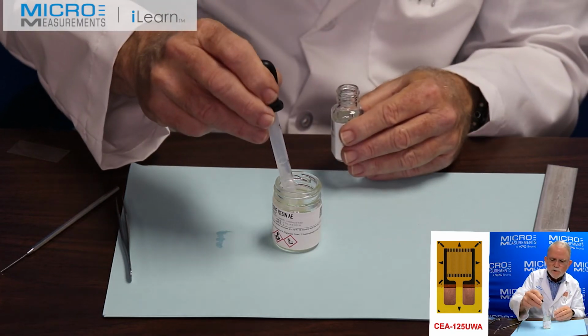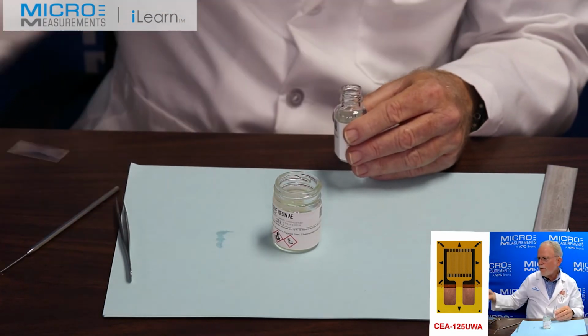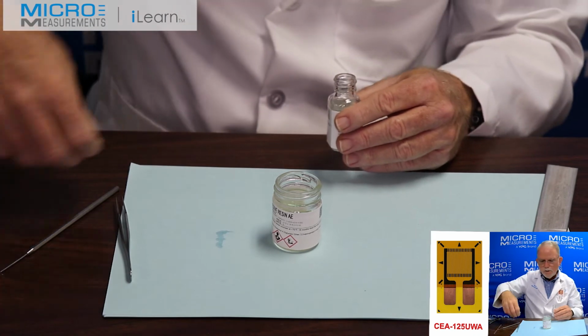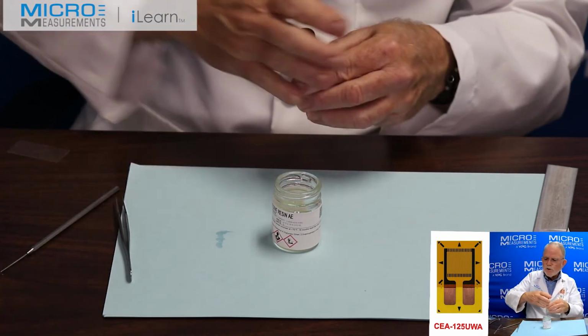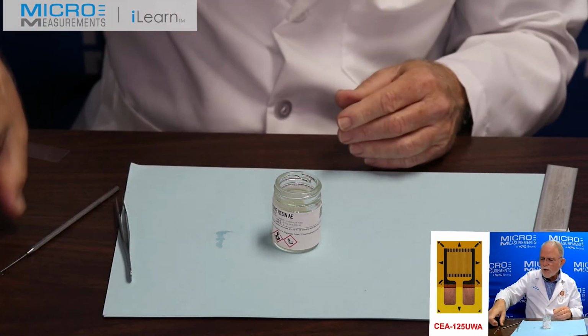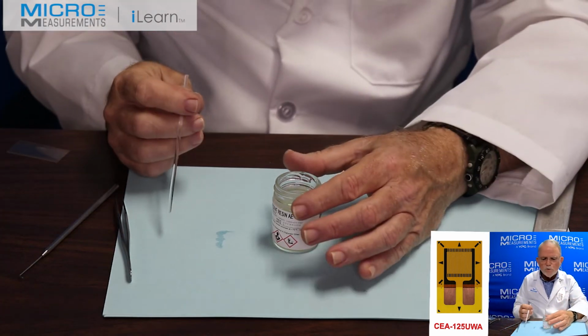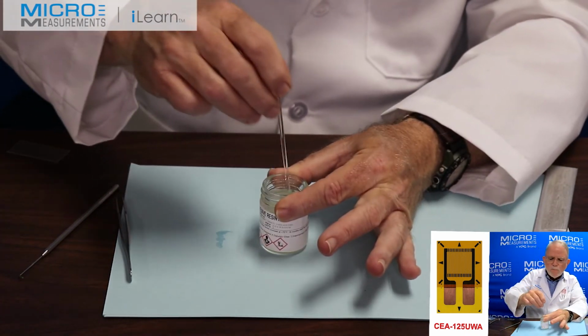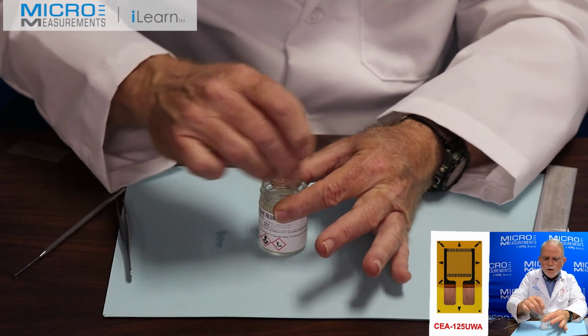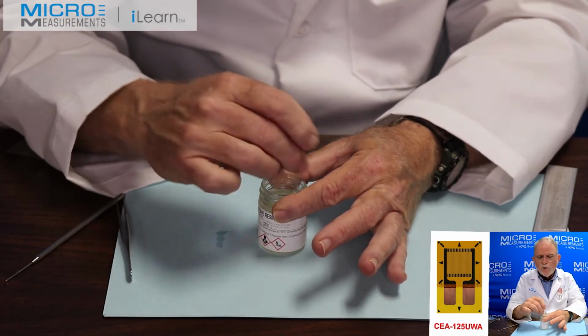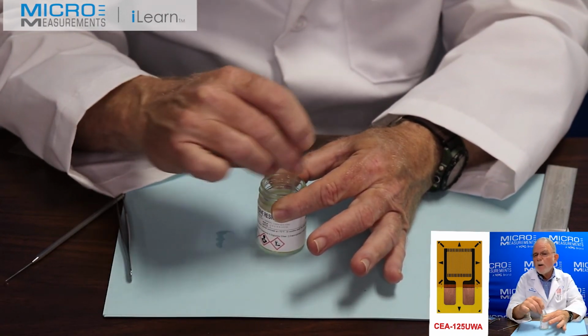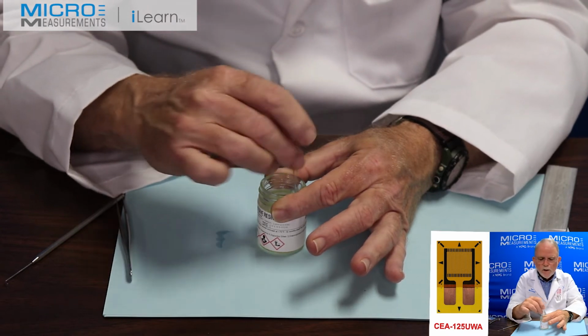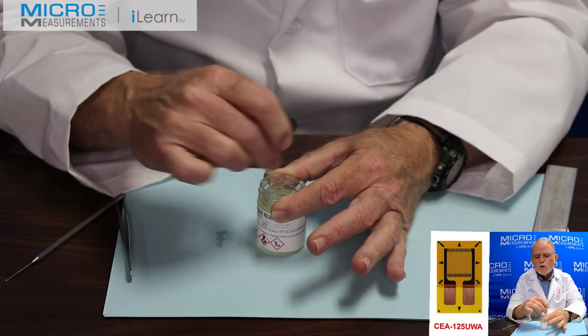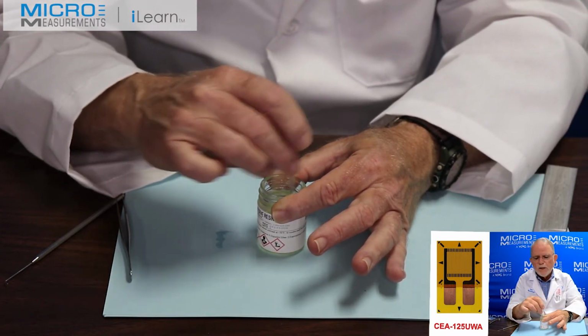Going to dispense that in the center of the resin jar. Immediately cap the curing agent because, as I said, it's very hygroscopic and you don't want it to absorb too much moisture. Take my hand and hold it by the top of the jar, and I'm going to begin stirring this. Now this material will actually mix together in probably about 30 seconds to a minute, but we will continue to stir it for a full 5 minutes.